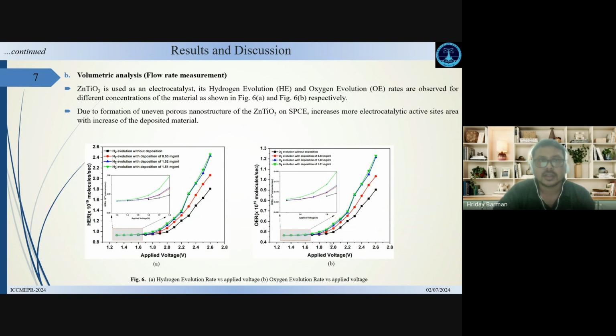Based on this analysis, we took the further measurement of volumetric analysis for the flow rate measurement, and this analysis has been done for the 3 different electrodes that we prepared earlier, at different concentrations, and also with the bare electrode, which is not deposited with the material. As we can see here in figure 6a and b, when we use the bare electrode, it comes into action after a certain voltage of 1.6 volt, as we can see in the small graph.